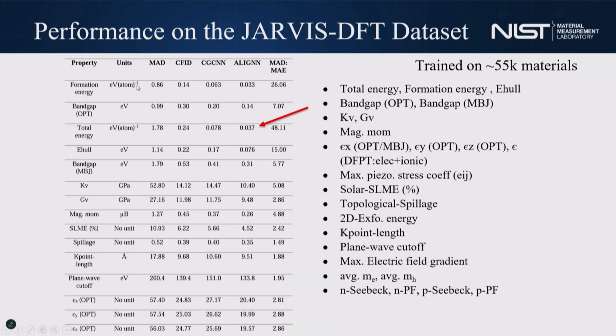Okay, so one of the first things we did is predicting the graph level property. So formation energy, band gap, and remember we talked about the baseline model. So the MAD here represents the baseline model. So the MAE, you can see for some of the properties 50, and for some it's like 1.49. So it shows that there are some properties of materials which are much easier to learn compared to others. Okay, so just because we have this angle doesn't mean we have solved the problem. There's still a lot of room for improvement.